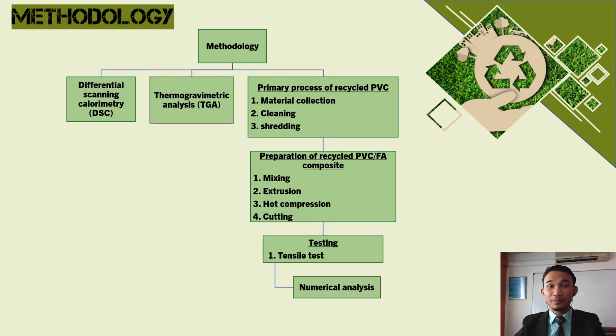After that, I go through the preparation of recycled PVC and fly ash composite process. The first step in the process is mixing. In this step, I prepare 5 different parameters, which are 100% recycled PVC, and 0, 5, 15 and 20% weight percentage of fly ash content in the composite. Next, I continue with the extrusion process. In this step, I use a hot twin screw extruder. The extrusion process was run in a temperature range of 175 Celsius and the speed of extrusion is set at 65 rpm. The composite was extruded in solid wire sheet.